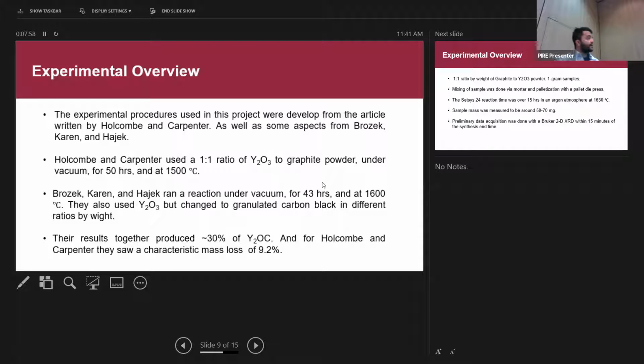For the Holcomb and Carpenter, they used a 1-to-1 molar ratio of yttria to graphite powder under vacuum for around 50 hours, which is a very long time, and at around 1,500 degrees Celsius. For Brozek and Hajek, like I said, they kind of ran a similar reaction, but with different reactants. They did the same under vacuum for 43 hours at a higher temperature of 1,600 degrees Celsius.